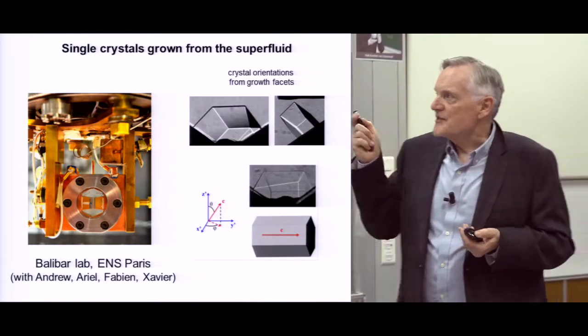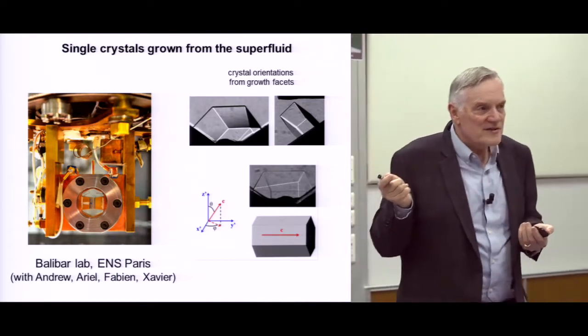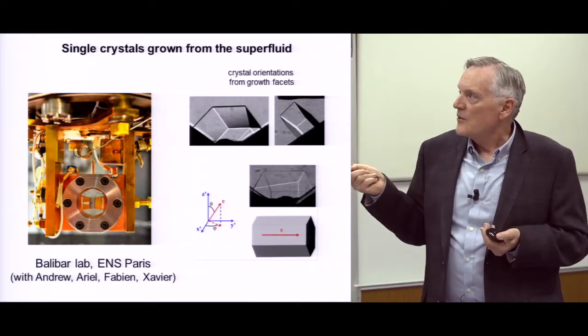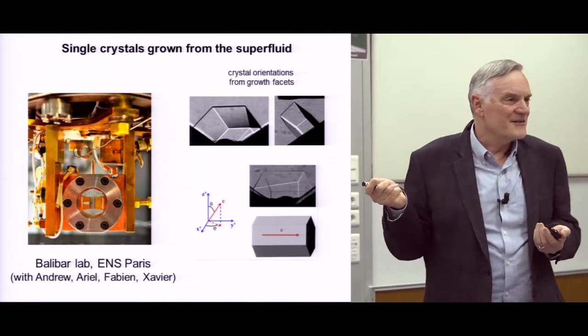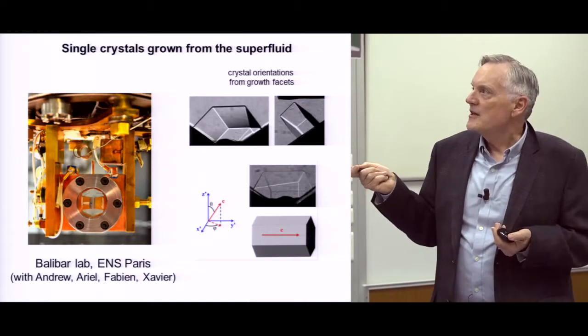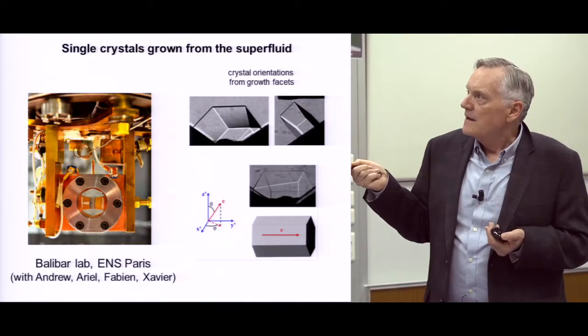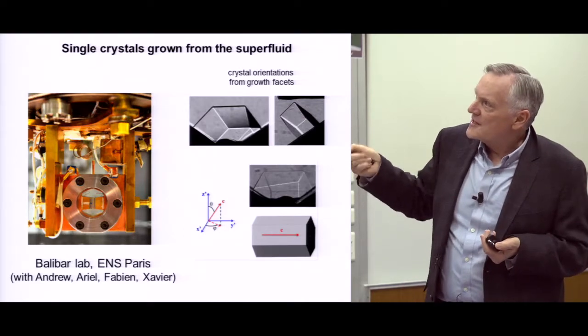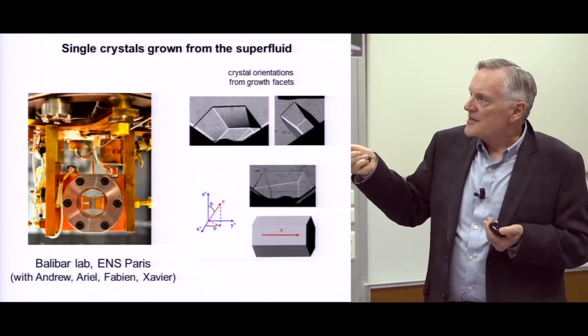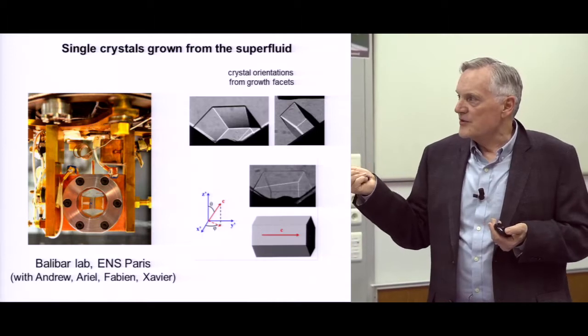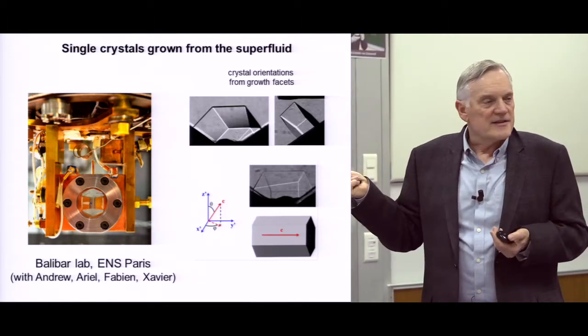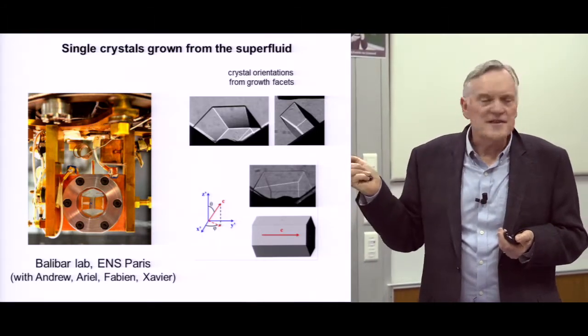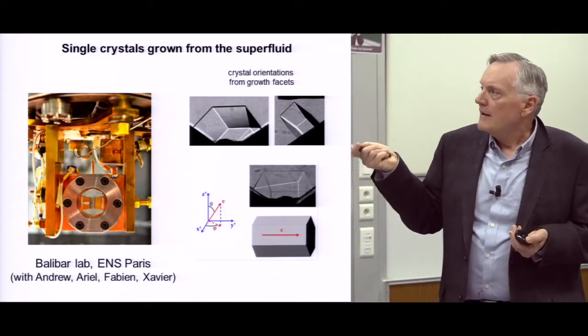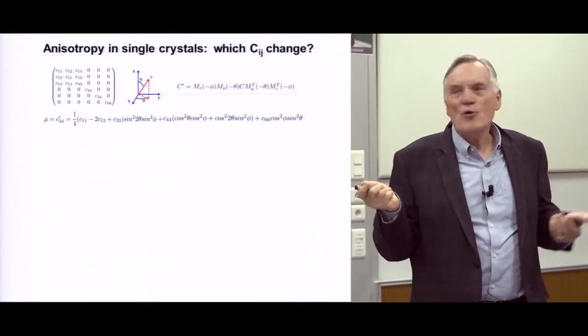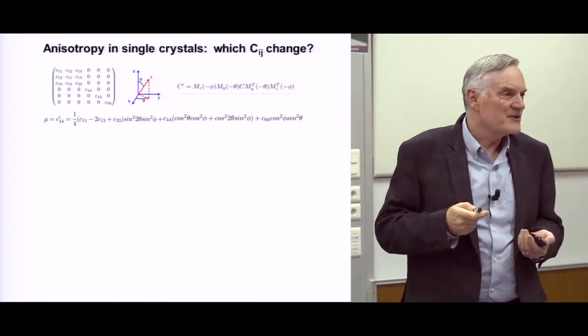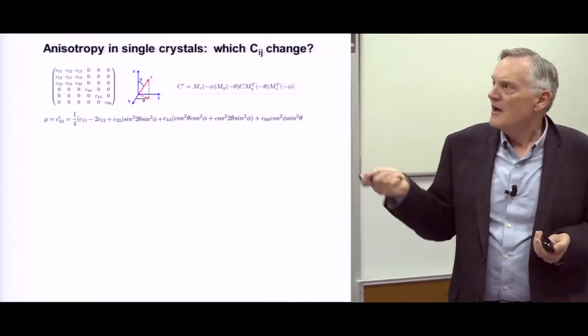But the beauty of this is that you can grow different crystals and they have different orientations. So with a little bit of effort, or a lot of effort actually, the graduate student grew a lot of crystals, you can see some examples. They're all hexagonal. Here's one that's sort of at 45 degrees, vertical is the c-axis. Here's one at some other angle. Here's one that's sort of lying horizontal at 0 degrees with respect to the hexagonal C-axis. So you've got a coordinate system. And if you know all this, now you can transform your experiment into your frame of reference if you want, right? Transform your crystal.